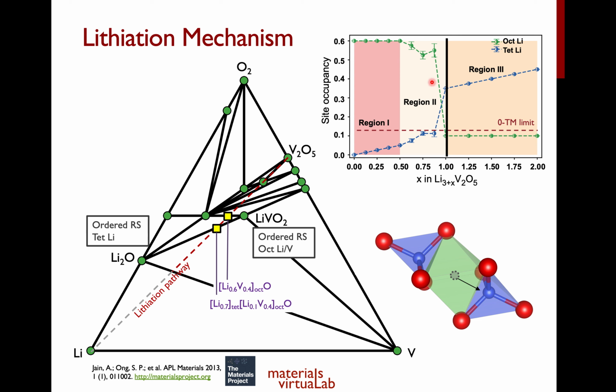So this is why in this region 2, you actually see that your octahedral lithium occupancy begins to decrease from 0.6. Initially, the decrease is fairly gradual, while accompanied by still an increase in tetrahedral lithium occupancy. Now the lithium tetrahedral occupancy actually increases at a slightly faster rate until you hit this Li4V2O5 composition. At Li4V2O5, you see a sudden complete rearrangement of lithium in the disordered rock salt crystal structure. You have this sudden drop in octahedral lithium occupancy, while you see this sudden jump in tetrahedral lithium occupancy. And you can understand this from the phase diagram, right?